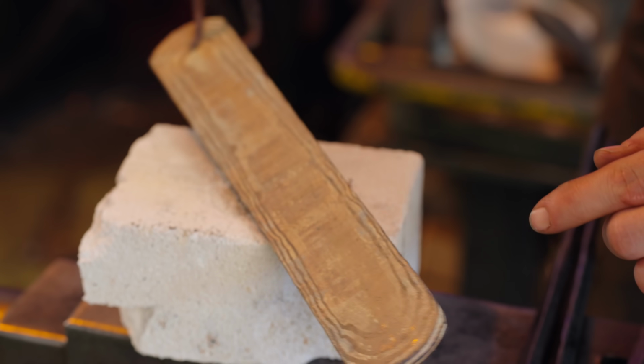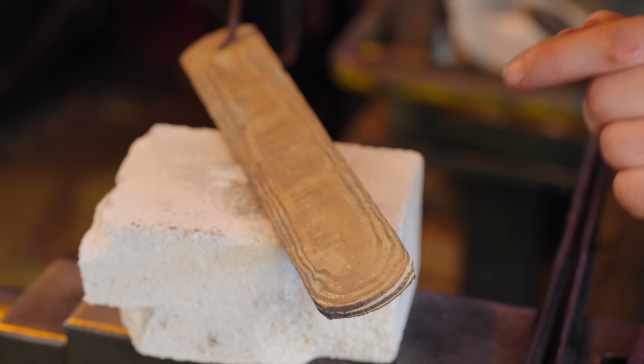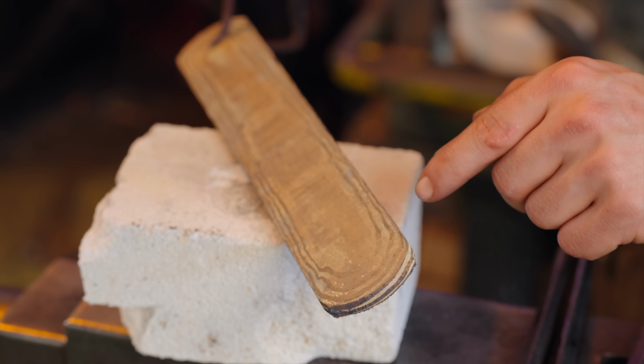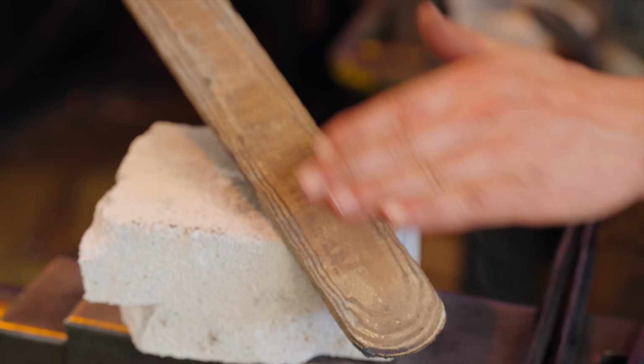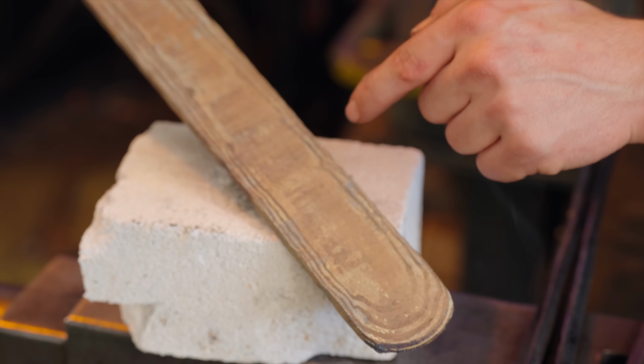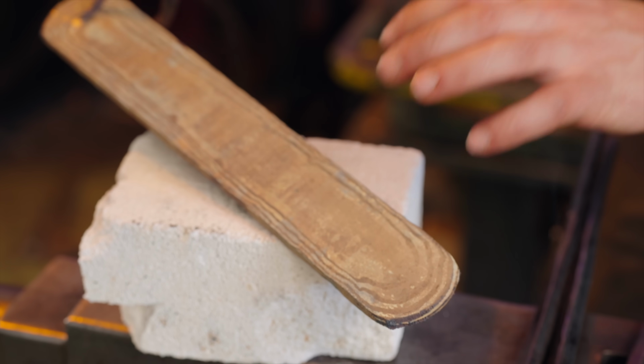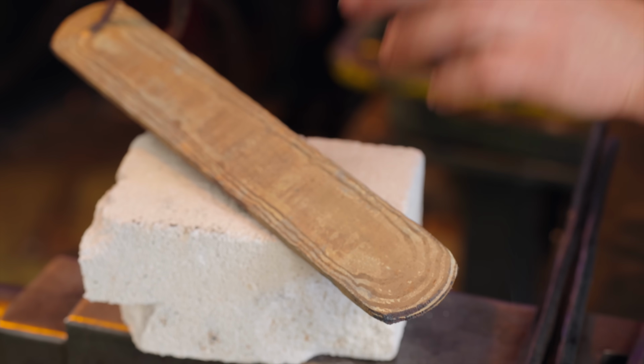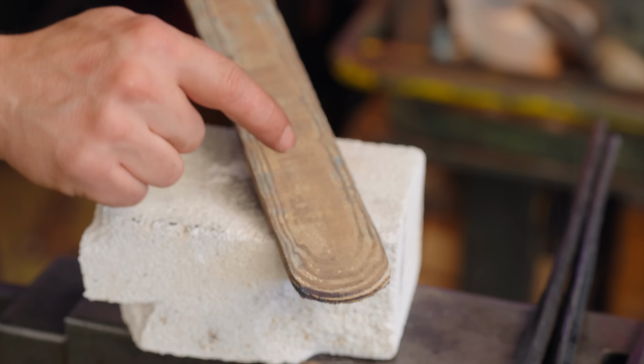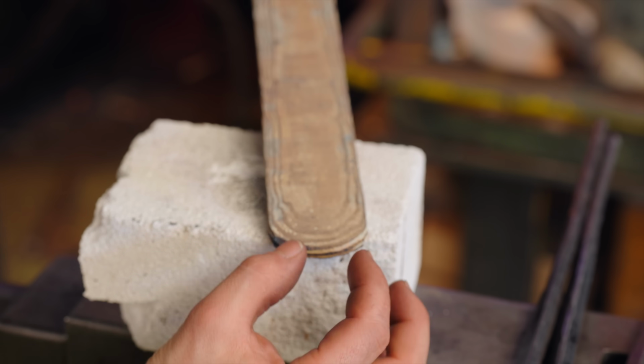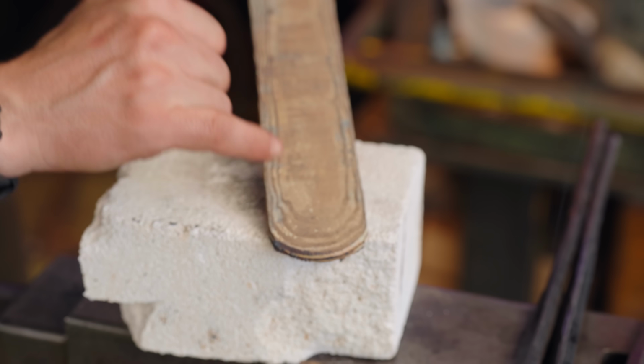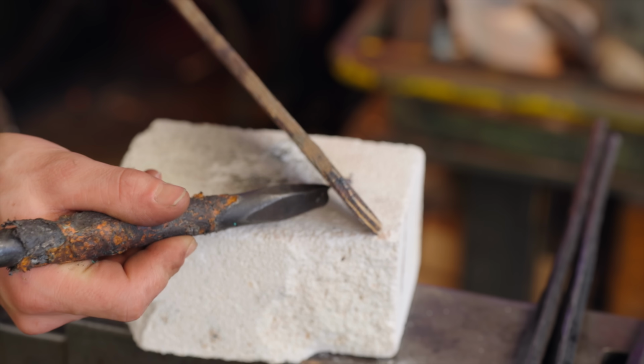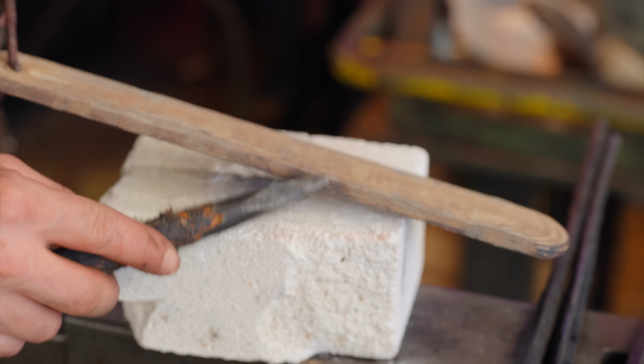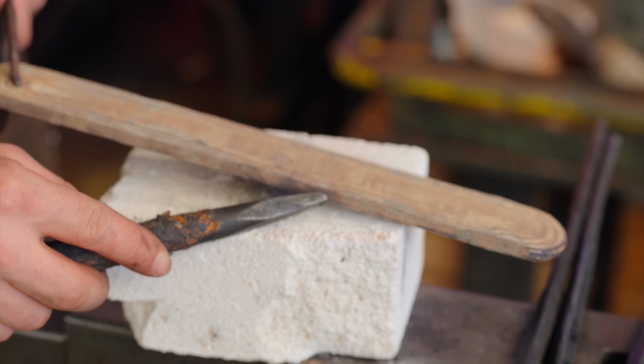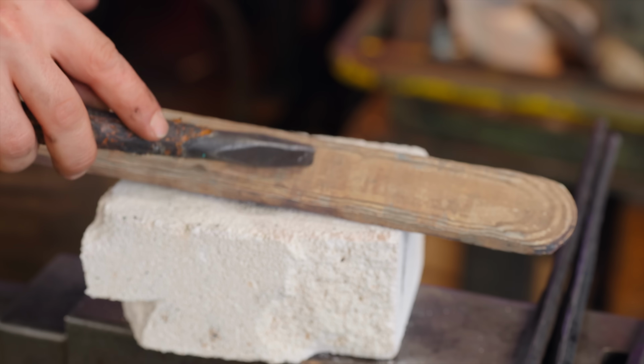All right, just got it forged out. So cool to see the pattern come through, but something kind of novel is happening here. You see how on this top surface, we are seeing the layers? That's not really ideal. This is moving in a different way to steel. What's happening here is the innards of it are squishing out further than the top surface is. And the downside to it is that we're not going to get the density of pattern in the edge that we otherwise might because it's being flowed up towards the top surface.